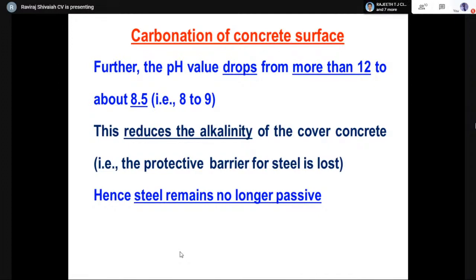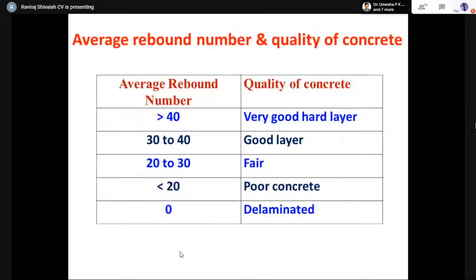And there is every likelihood that at all concrete surfaces where it has carbonated, the reinforcement starts to corrode. So you need to understand, if you take rebound hammer readings on carbonated concrete surfaces, we are going to get higher rebound numbers, and we should not be misled into saying that the strength of the concrete is quite good. So in general, if you have rebound numbers of more than 40, we can assume that it is a very good hard layer. 30 to 40 good layer, 20 to 30 fair, less than 20 poor. And if you get zero, you can easily understand it has already delaminated.